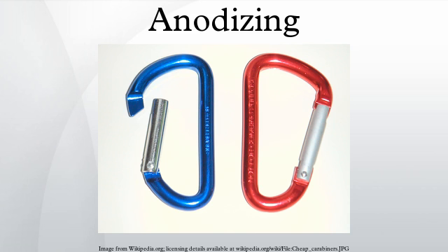The number of dye colors is almost endless. However, the colors produced tend to vary according to the base alloy. Though some may prefer lighter colors, in practice they may be difficult to produce on certain alloys such as high silicon casting grades and 2000 series aluminium copper alloys.